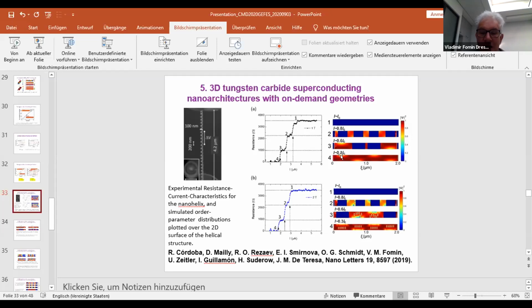This suggests the following scenario: when the transport current is not that large, we have some distribution of the parameter according to the inhomogeneity of the magnetic field, which is very strong in this system. At higher magnetic field, there are even vortices, as shown here in the lower panel, but they do not contribute too much to the resistance. If we increase the transport current to a certain value, they develop phase slips in some windings, and certainly these phase slips induce voltage. In other words, they produce dissipation, and this is seen as a first shelf in the resistance current characteristic.